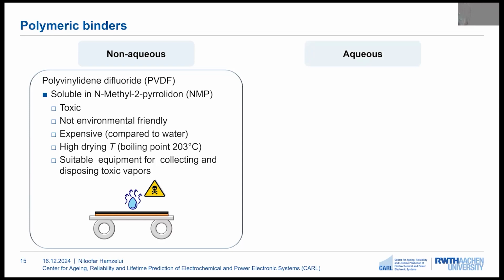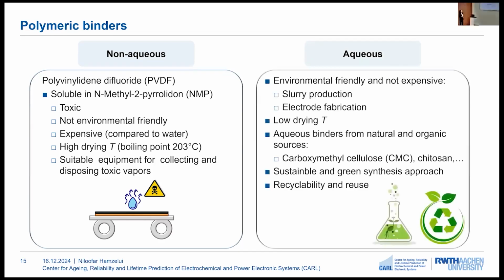On the other hand, we have the aqueous binders. Aqueous binders are more environmentally friendly, and they are less expensive and require lower drying temperatures for the electrode. Some of these aqueous binders come from natural sources, such as carboxymethyl cellulose or chitosan, so this results in a more green synthesis approach of the binder, and also this would be an advantage later on during recycling of the battery.